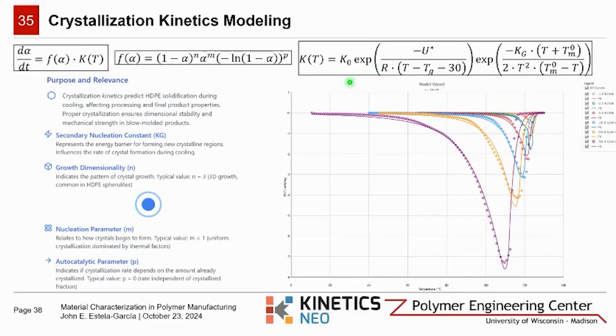When we combine these two models, we can quantify the differences in crystallization behavior between the virgin and recycled materials across a range of temperatures and degrees. So this approach allows us to optimize cooling profiles and processing conditions for each material, ensuring consistent product quality. We will particularly be paying attention to the Nakamura coefficient, or the secondary nucleation constant here, as that one is indicative of the crystallization behavior. It's representing the energy required to form these fine crystals.